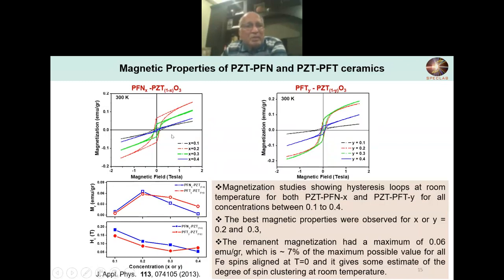Coming to the magnetic properties, you can see that the room temperature magnetization and also the remnant magnetization exist. These loops are the indicators of that. And here also for 0.2, perhaps the best magnetization was there in this case. So 0.2 and 0.3 we consider probably the most suitable materials for further studies.